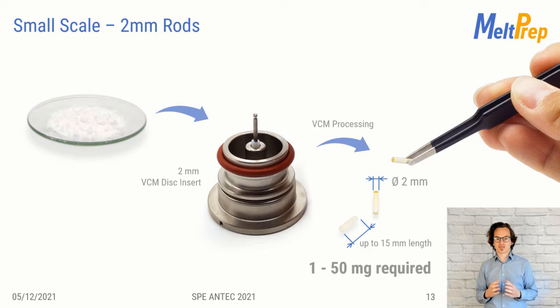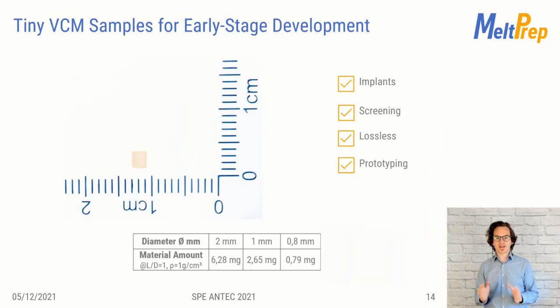This is a game changer. But we did not stop here. We recognized the need for even smaller tools with even lower material requirements. Let's imagine samples with a length to diameter ratio of 1 and a 1 gram per cubic centimeter density as an educated guess for a polymer density. When we look at the 2 mm sample, we would only need 6 milligrams. For a 1 mm sample, it's already less than 3 milligrams. For 0.8 millimeter, less than a milligram.